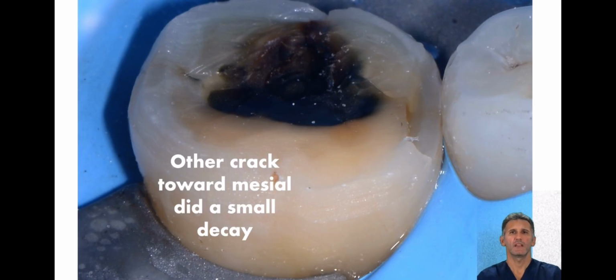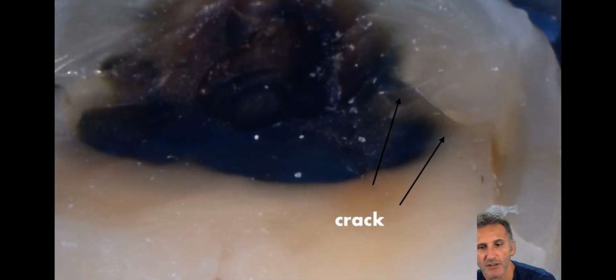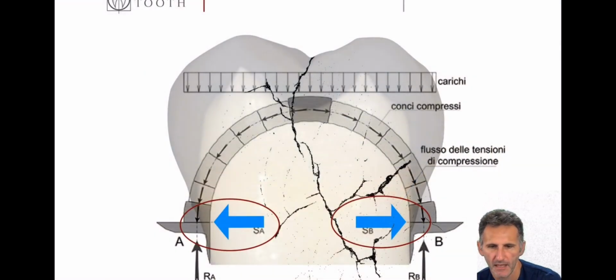So, what do I do? I try to change how load is applied to this material, changing the conformation. I did a flattening of 2 millimeters. I did, if you see, a small bevel, in order to give a different kind of force, more compressive, to this tooth. And I did a direct overlay in a case like this. You see that there is a crack also here going to the mesial, and this is what happened.